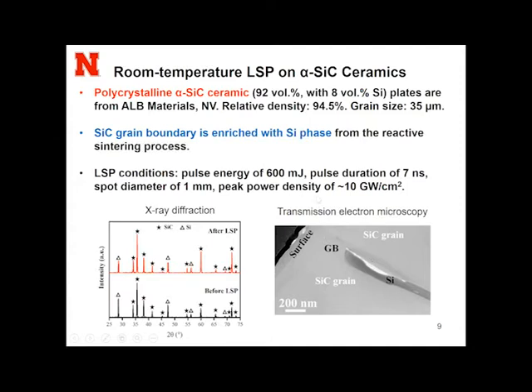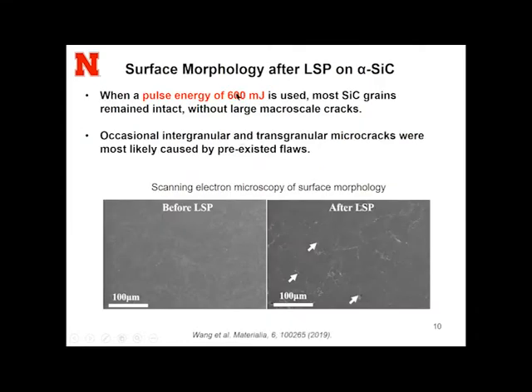But we conducted laser shock peening in the following condition. Here, this is the optimized condition. What we found is that pulse energy is a very important parameter to control the surface morphology and the damage. If the pulse energy is too low, then the peening effect is also very low. But if we use a very high pulse energy, then it can generate a large number of cracks on the surface, which gives us a negative effect. So there is an intermediate energy, and in this case, we found 600 mJ is the best pulse energy for